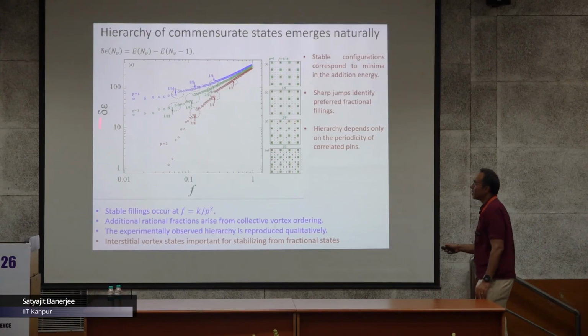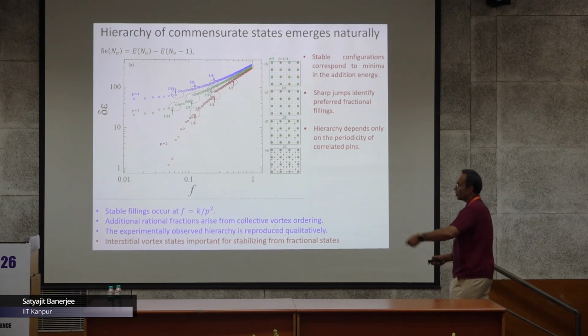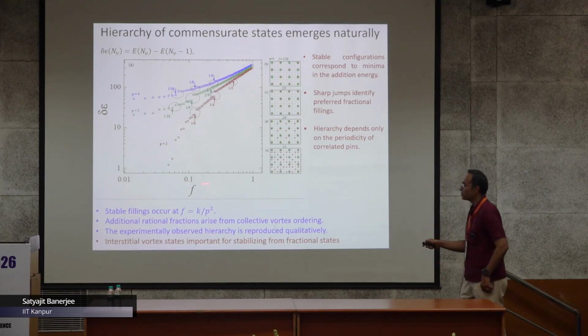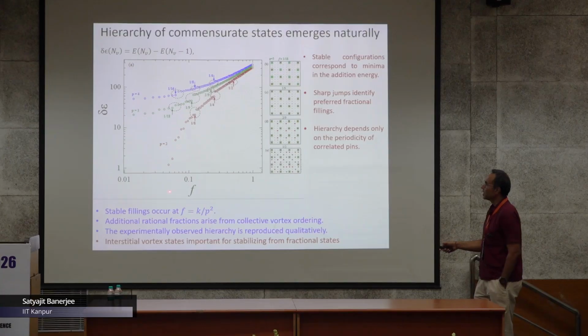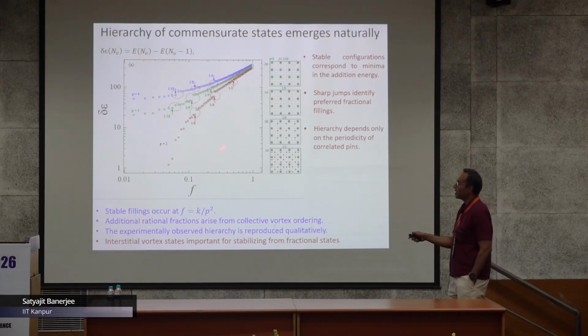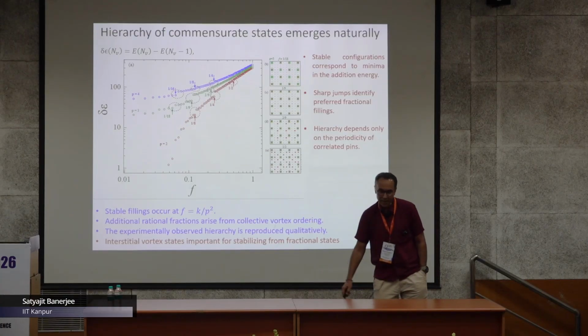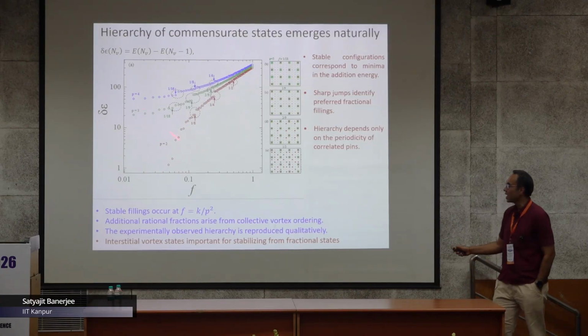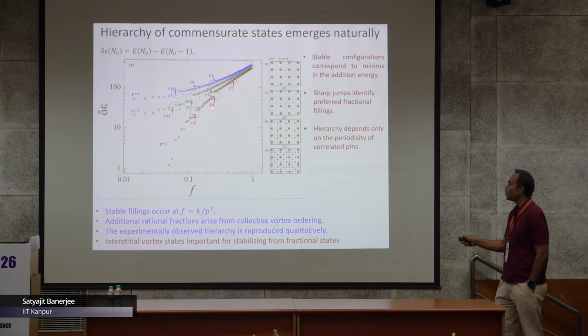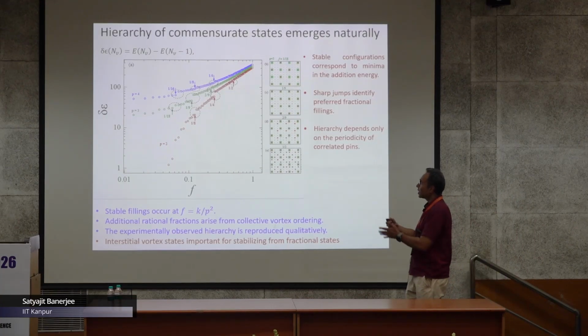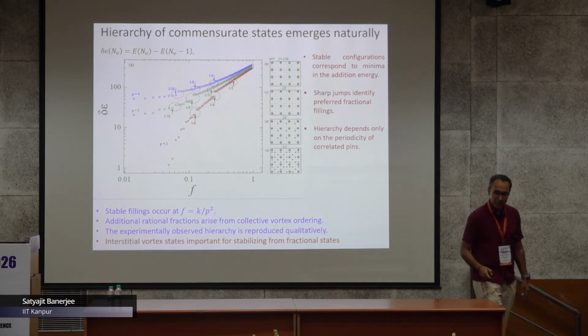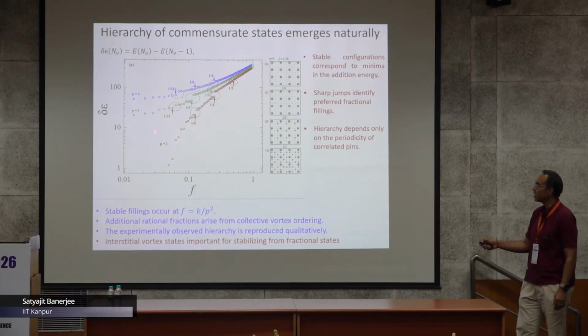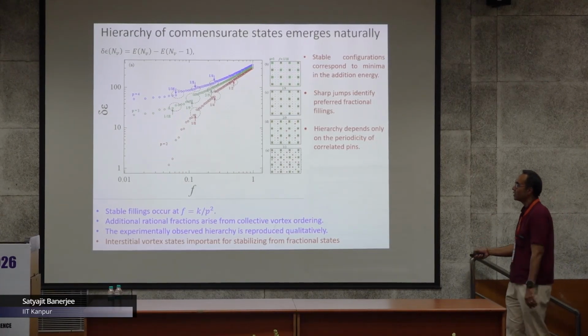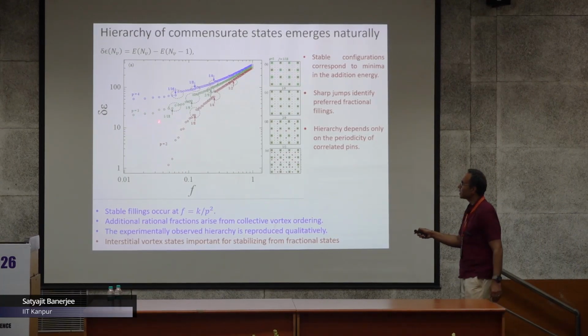If you look at the energy cost of putting a vortex inside the crystal as a function of filling fraction—how many periodic pins are filled by vortices—you see kinks in this change in energy. These kinks occur at fractions of 1 by 8, 1 by 4, 1/2, so there's a full hierarchy of filling fractions, and these can change as you vary the periodicity of the periodic pins inside the crystal.